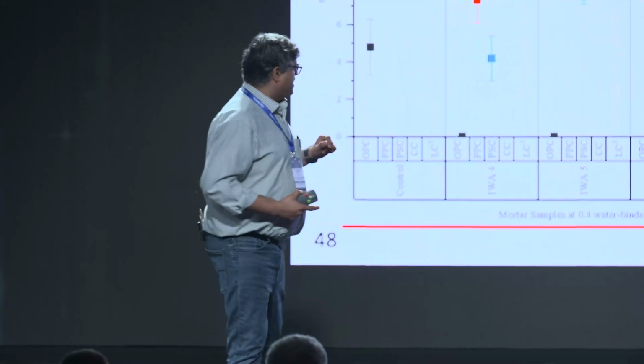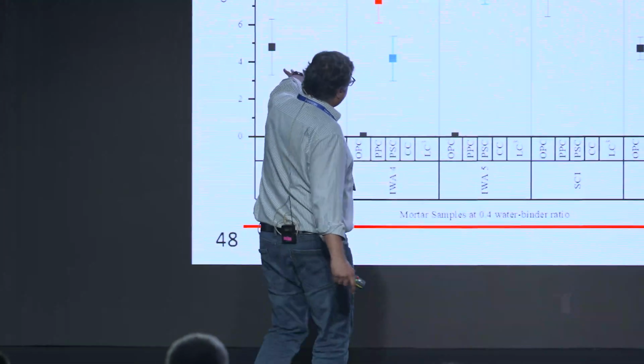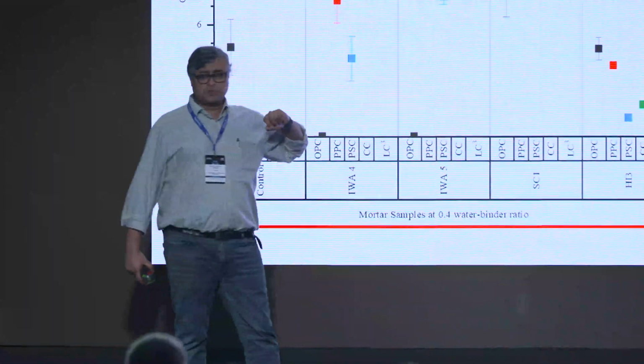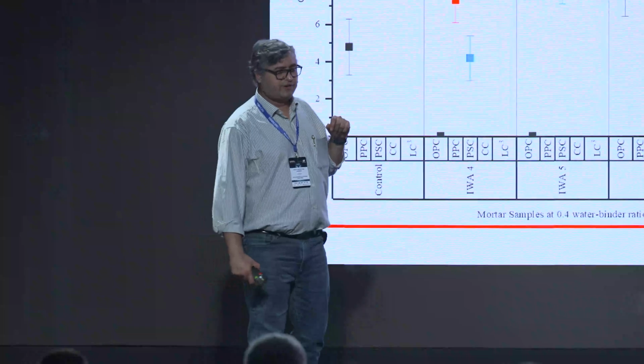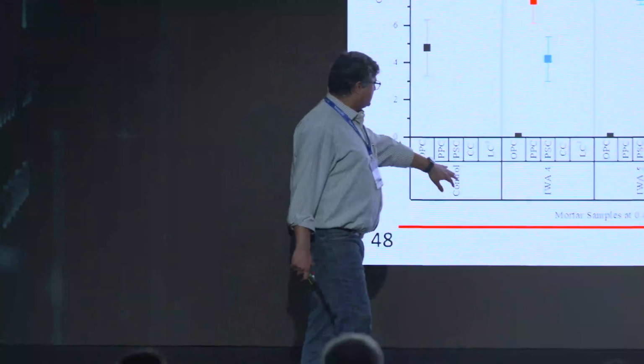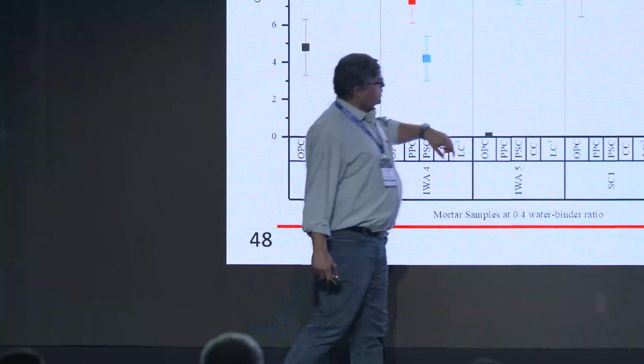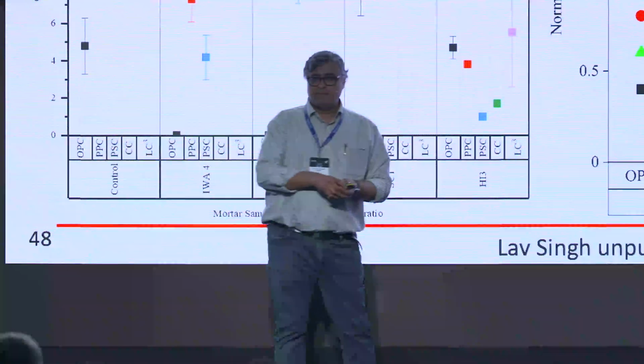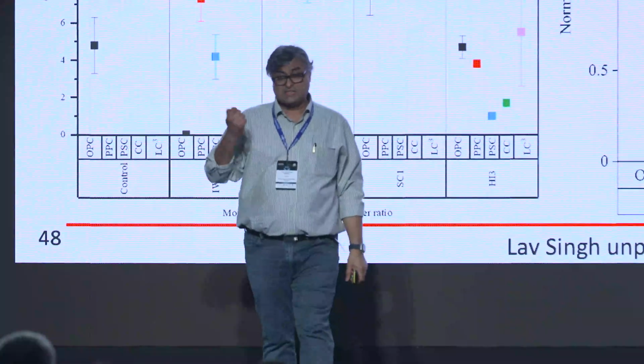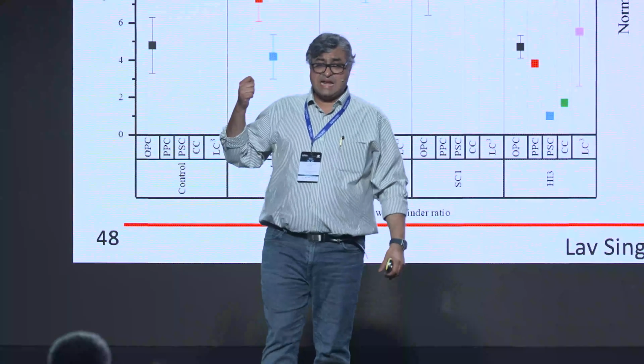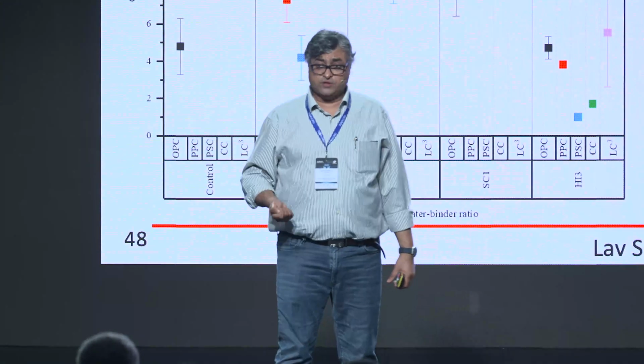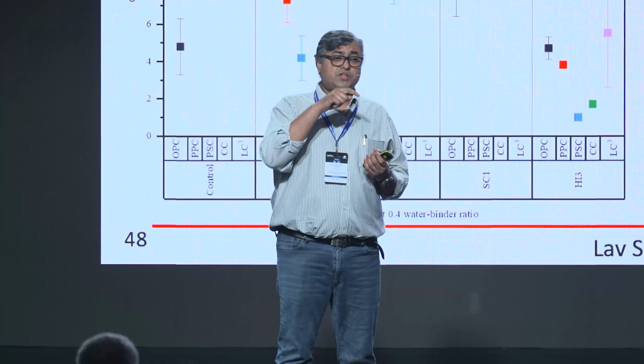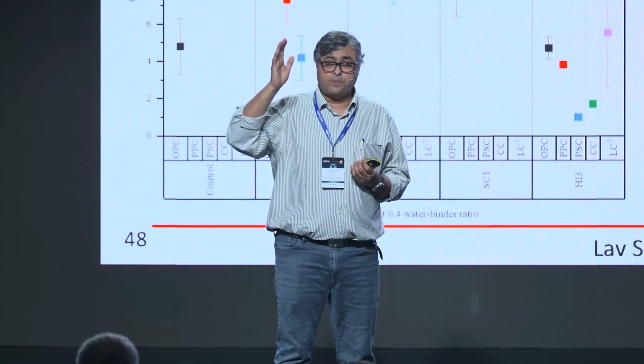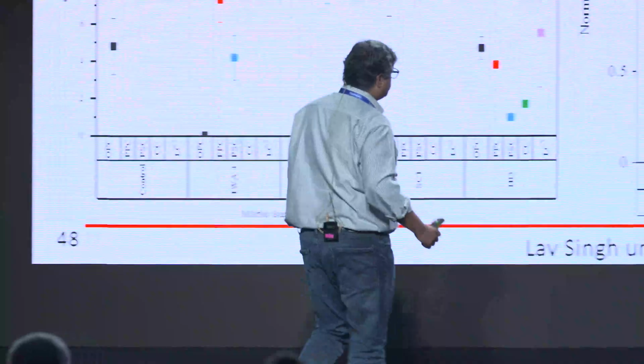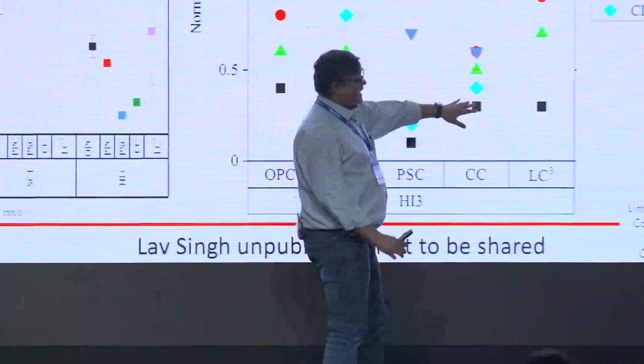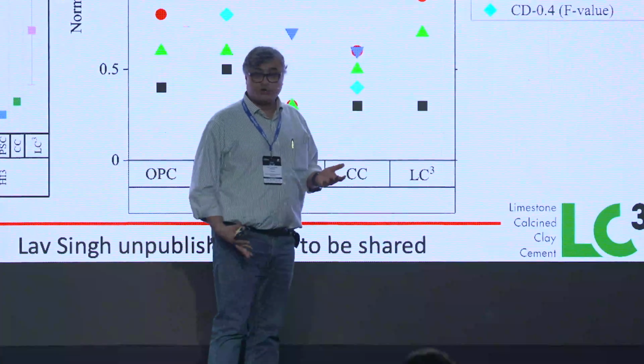For example, this is a case of carbonation depth, and that is how much transport happens in concrete, measured using different tests. To be very simple, this is an LC3. This one over here is an LC3 with a certain chemical simply painted onto the concrete. This is a silane that has been impregnated from the surface of the concrete. Not only does the carbonation depth in the concrete reduce if you're painting this on the surface, the transport properties of the concrete also reduce. That means the risk of corrosion reduces significantly.